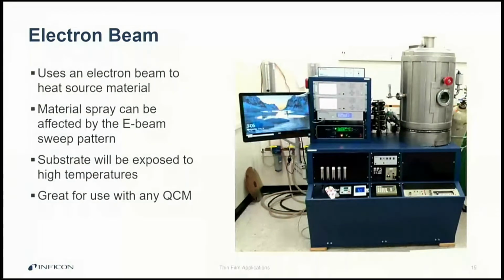It is important to note that the sweep pattern that you use on your electron beam sweeper will affect the spray of some materials. This is most commonly seen with materials that sublime or that are known to have very directional evaporations or sublimations. As with resistive heating applications, a substrate is going to be exposed to high temperature, so that's something you'll need to keep in mind. And also, like resistive heating applications, a QCM is a great addition for an electron beam evaporation.